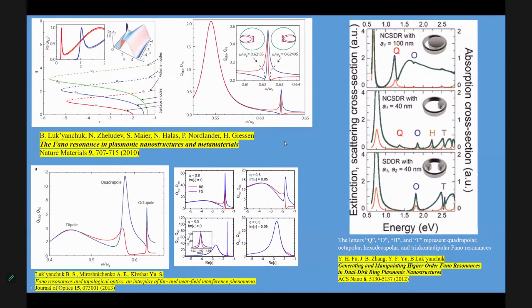So if we use Mie theory, then we can find that at a size parameter close to 10, and it also depends on the refractive index, you can generate optical vortices, and many papers were published on this.